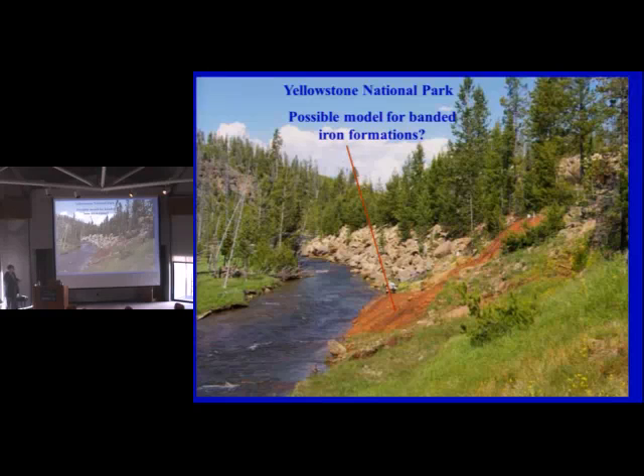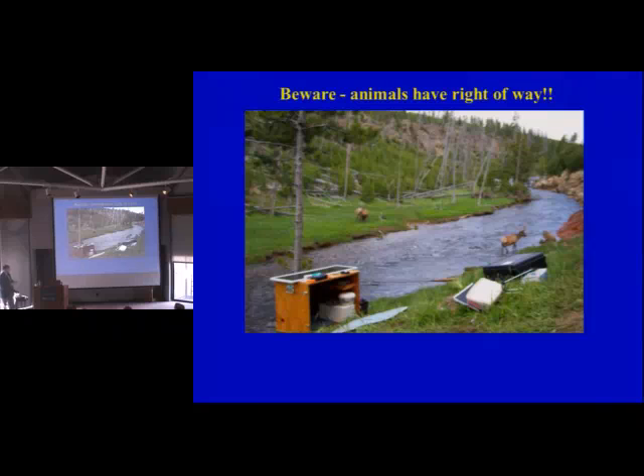That's iron-3 precipitates. And I'm going to show you how the system looks. There's a fair amount of iron going into the stream from the source waters. It's one of the few times that I've actually left equipment because we were almost attacked by these elk. And you can see that things are slightly in disarray. And what you see here is our lab-based equipment.